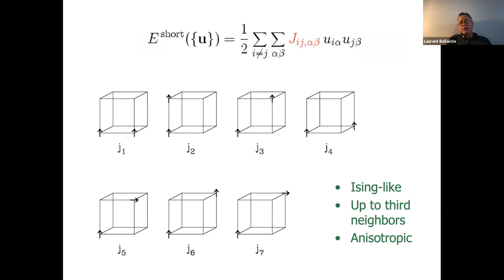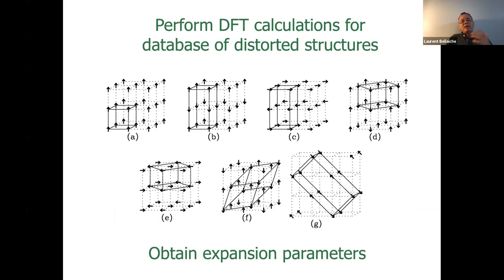And you go to third nearest neighbors, and it's highly anisotropic. It's quite different than a magnetic system. And then you use DFT calculations to get these parameters. For example, if I want to get the J parameters, I do this kind of simulation where the dipoles are differently oriented, and you get these J1, J2, J3, J7 parameters.